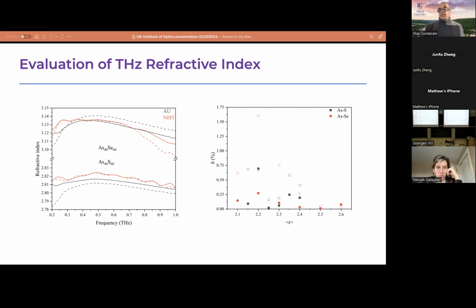It turns out that the error limit is predominantly less than 1% in all of our measurements, except in one case. So this is one way to let you know glasses prepared anywhere can be tested somewhere in a standard lab. We wanted to make sure that the features we are seeing are reproducible in another instrument.